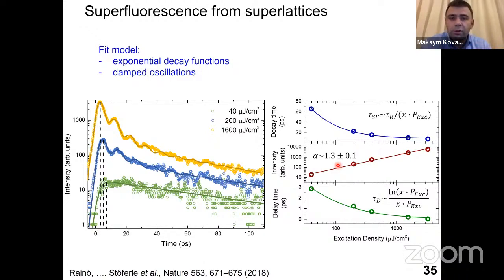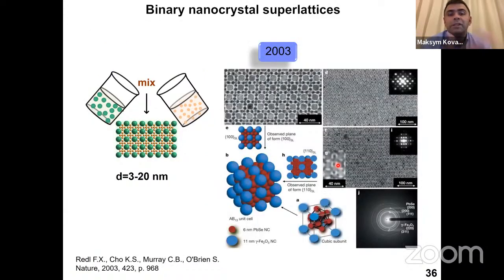So this property is called superfluorescence, and we were very excited to observe that because it's simply the first chemically produced quantum dot system which exhibits this property. So far, it had been observed in very few cases, which is epitaxial quantum dots of one kind, as well as some of the atomically doped alkali metal halides, or even in some of the gases such as hydrogen fluoride. But now you have a solid state system where you can potentially tune this property through composition, through size, through nanocrystal assembly, and you can basically engineer this property. It's not that you can just observe it. And so we were extremely motivated to try to engineer this property further.